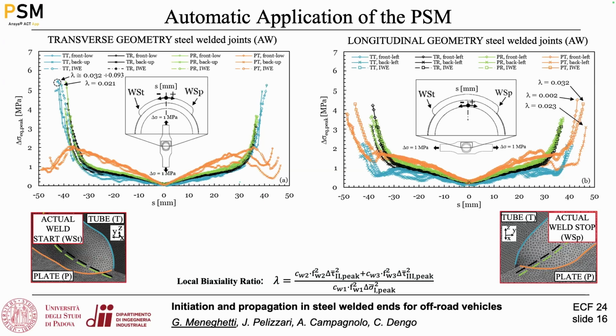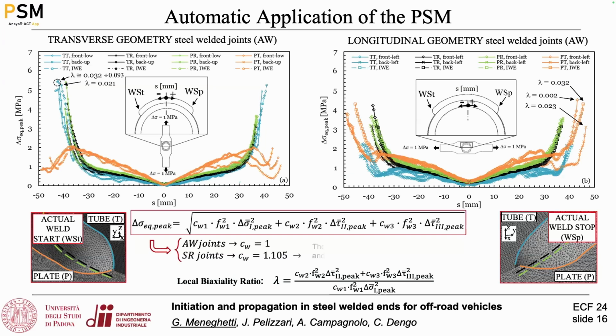And if you remember the dye penetrant I showed you before, the crack just started from here and then propagated out of the weld toe. So the peak stress method correctly estimates the crack initiation point. This is the first good news.